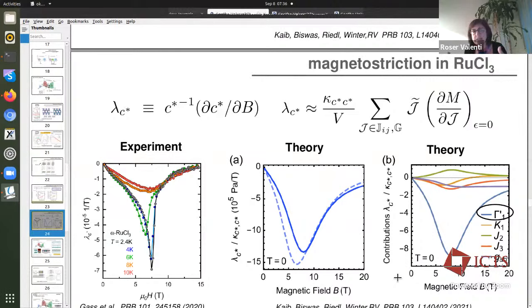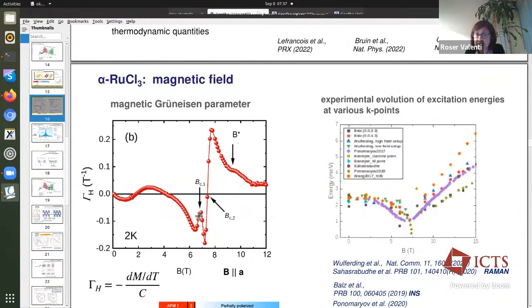But the physics is an issue of energy scales. As long as the energy scales of the two-dimensional case are much larger than the three-dimensional case, you don't have to worry about them so much. Only when you have, let's say, magnetic fields, or you are applying an external perturbation where your scales are being reshuffled, then you should pay attention to this third contribution. And this is seen, in fact, in this experiment, where was my Grüneisen parameter, for instance? Exactly. The fact that there is this phase here is because you start to have a Q vector where the stacking in the third direction is important, because you are defining a magnetic order along the Z direction as well.